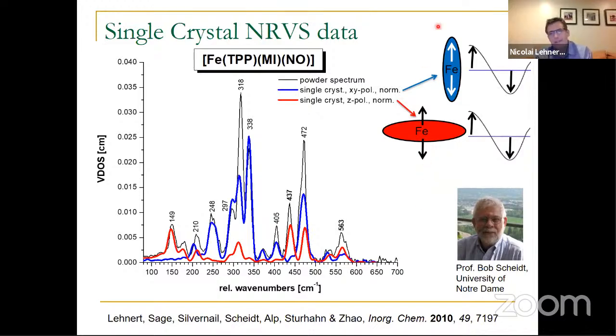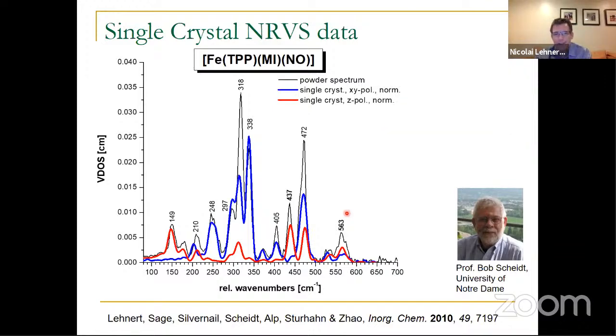Right? And so by doing the single crystal experiment, we can distinguish vibrations where the iron moves in the plane of the heme from those where the iron moves outside of the plane of the heme. And of course, for the iron-NO stretch, the iron will move perpendicular to the plane of the heme. For the bending mode, it will move in the plane of the heme. So if you look at the data, you can see the band at 437 wave numbers has strong out-of-plane intensity and almost no in-plane intensity. So we can see this is the iron-NO stretching mode, where the iron moves out of the plane of the heme. Okay? And 563 is the other feature, the other feature that is isotope sensitive.